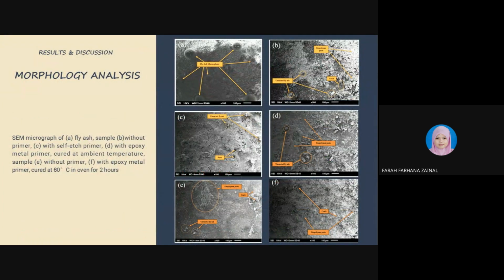Then this is the morphology analysis. As we can see from the morphology analysis, A is the fly ash sample, B is without primer, C is with self-etch primer, D is with epoxy metal primer, E is without primer, F is with epoxy metal primer cured at 60 degrees Celsius in oven for 2 hours.